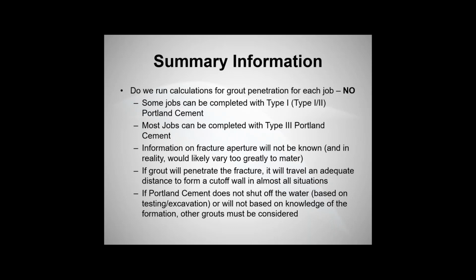I think the other really important thing to realize is that the distances provided in the previous chart demonstrate that if a particulate grout will go into a feature, a fracture, then typically it's going to travel far enough to be effective. For grouting purposes, we generally assume that grout is going to travel about 8 to 10 feet. So we're very conservative on the distance that we assume it's going to travel.